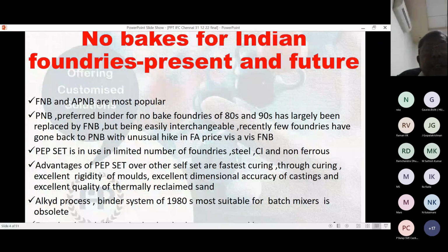PEP set is in use in a limited number of foundries, to my knowledge, in 2 steel foundries, 2 cast iron foundries for making only cores, and 1 non-ferrous foundry. Advantages of PEP set over other self-sets are fastest curing. This is the fastest self-set on the earth, and curing speed matches almost to gassing systems. The molds made out of this system are extremely rigid with exceptional dimensional accuracy, and castings are also very much free from surface defects and dimensionally very much accurate.